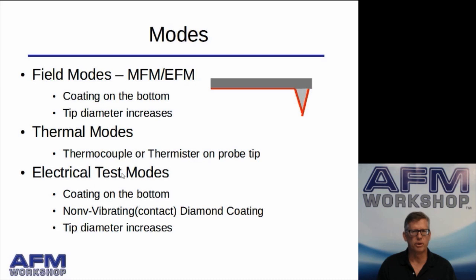Finally, electrical test modes. This could be conductive AFM or measuring parametric measurements. You put a coating on the bottom, just like this here, shown with the red. And again, most of these electrical test modes quite often are done with non-vibrating or contact mode. So it can be quite good to use a diamond coating for these measurements, because the diamond coating is much stiffer and the coating won't be rubbed off while you're scanning. But again, always remember the tip diameter tends to increase when you put these coatings on.